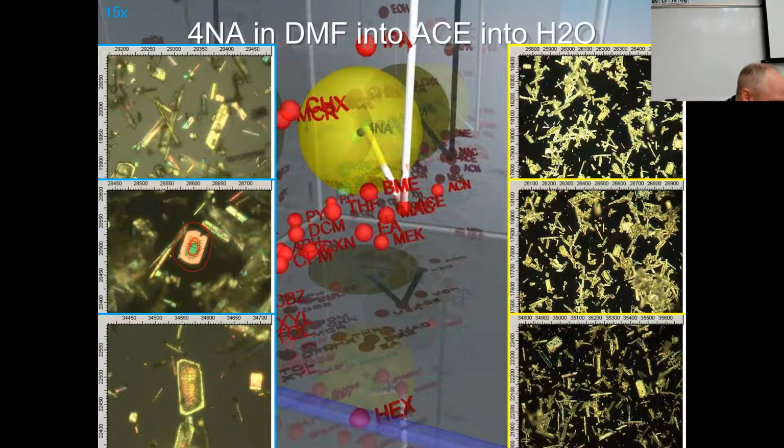So you had solvent stuck to that surface for quite a while as the crystal was growing, and then finally they left behind pits. Okay? So that's really confirming that this solvent is stabilizing that face. So our idea is sort of confirmed here. We still don't know what that face is with our X-ray crystallography, but our idea that solvent is going to stabilize the face that gets expressed is shown here with this solvent pitting. And so that's nice.